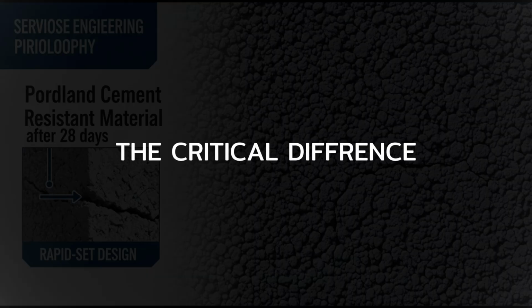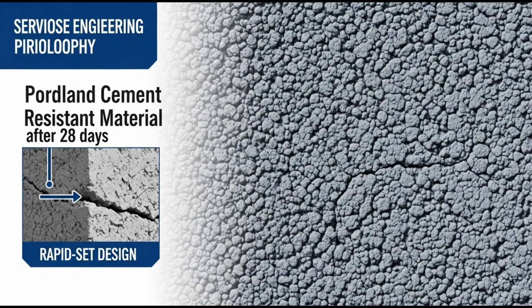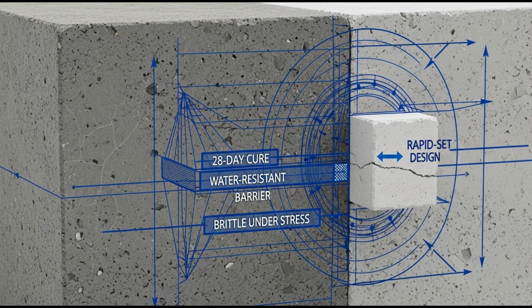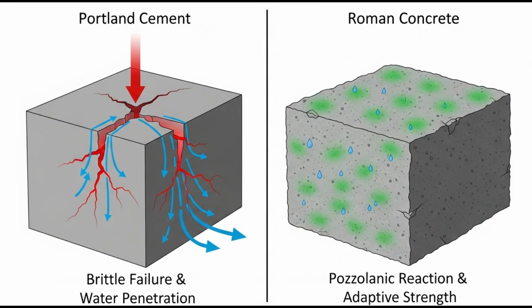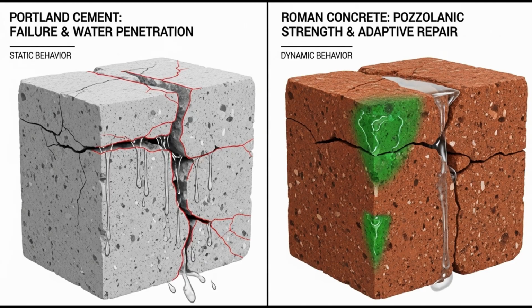The critical difference. Portland cement fights nature. It's designed to set quickly, harden rapidly, resist water once cured, but it's brittle. Cracks under stress. Those cracks allow water penetration. If rebar is present, corrosion begins.